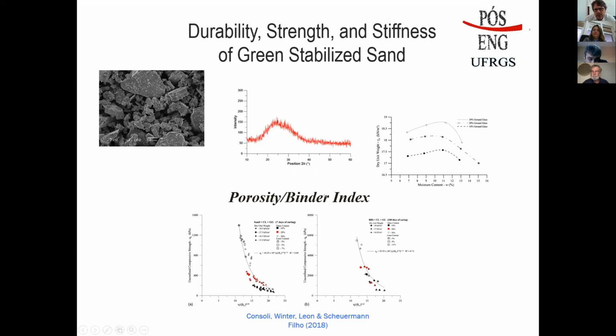Then when you put any kind of binder, in this case the binder that we are studying is this ground glass with lime, any kind of lime, even the eggshell lime or carbide lime, which is also a residue. We can have, and that's the position here, eta is porosity, BIV is the binder volumetric content, let's say. We can show that whatever you choose to compact, having different dry unit weights, different ground glass contents, and also different lime contents, you have a unique or nearly unique curve here that correlates this index